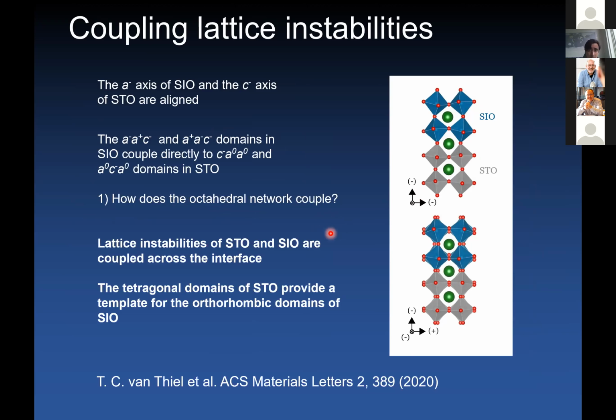So essentially the A-, A+, C- and the A+, A-, C- domains in SIO couple directly to the C-, A0 domains and the A0, C-, A0 domains of STO. So there's a direct coupling of one type of tetragonal domains in the STO with one type of orthorhombic domains in the SIO. So two lattice instabilities across the interface have been directly coupled. So STO is really providing a template along which the orthorhombic domains of strontium iridate can arrange themselves.